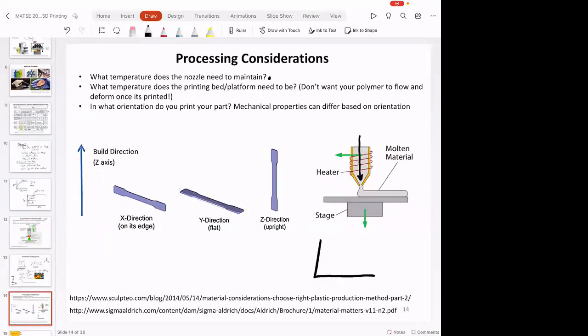It's not creep because it's not really solid. But if we look at the modulus versus temperature, remember we have glassy, here's the Tg, and then we have a roll off out here at high temp. This is liquid. This is rubbery. This is glassy. And so modulus, when it's flowing, is called viscosity. And so if we back off on the temperature, the modulus of the polymer goes up a little bit. And so effectively, it won't creep, or we don't get stress relaxation as fast if we decrease the temperature. Good. And of course, if we're not getting enough material flowing out of the heater, we turn the temperature up because we want to decrease the viscosity or make the polymer more liquid-like in order to get it to come out of that nozzle.